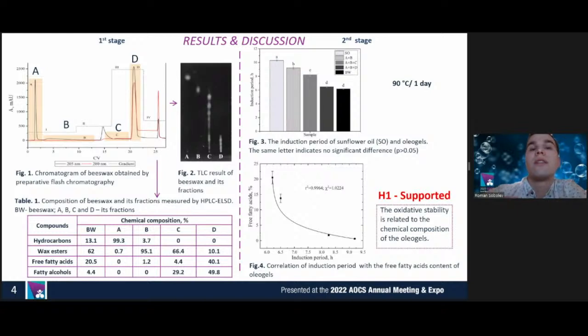In this work, we used beeswax and a combination of its fractions AB, ABC, and ABD as a gelator. Fatty acid analysis showed no significant differences among the samples. Figure 3 shows the analysis of the induction period of the samples. We show that the initial sunflower oil had the highest stability during oxidation above the melting temperatures. Oleogels on beeswax and the combination ABD fractions were the least stable. Correlation analysis of the induction period with the content of free fatty acids revealed a close inversely proportional relationship. The findings support hypothesis one, that the composition of the oleogels, regardless of texture, influences oxidative stability.